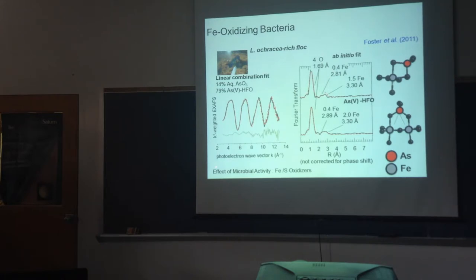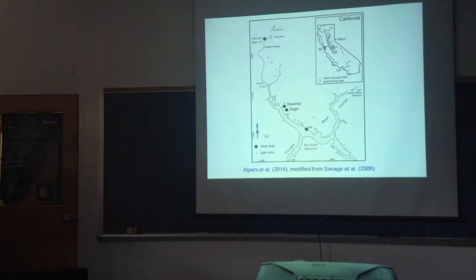oxidized form. There's also a microbial effect here because the reason these flocs exist is because of iron oxidation by microbes. So in studying these systems in detail, one really does need to consider the microbial activity as well. But it mostly affects iron cycling. Microbes will also affect arsenic cycling. The oxidation of the arsenic itself is mediated by microbes. And there's some microbes that actually reduce arsenic back down. So it gets very complex when you start getting into all the possible microbial interactions.